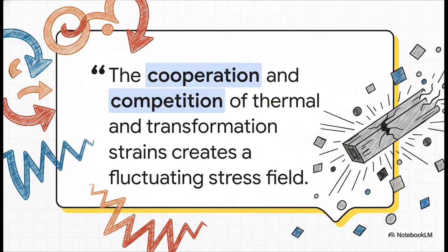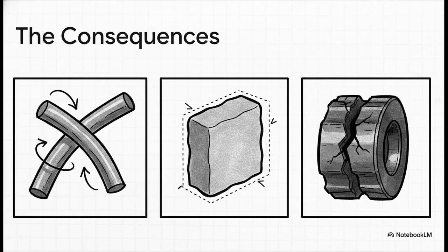This quote from the source material just sums it up perfectly. You get this chaotic cooperation and competition between shrinking and expanding forces. And what that creates is this fluctuating, totally unpredictable stress field deep inside the metal, which, as you can guess, can very easily lead to a catastrophic failure. And if that internal war is lost, well, the consequences are pretty devastating.